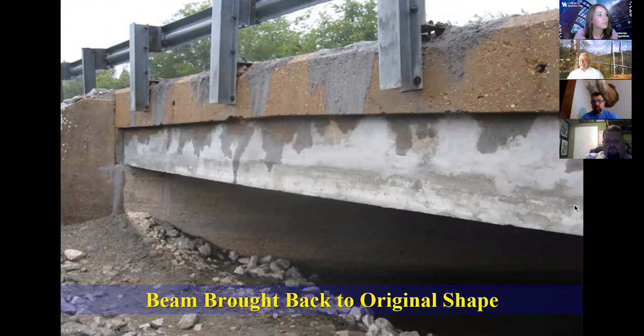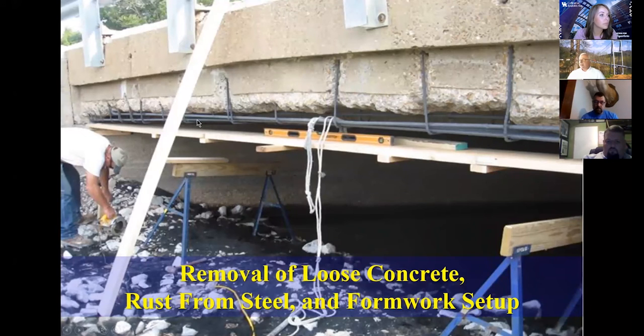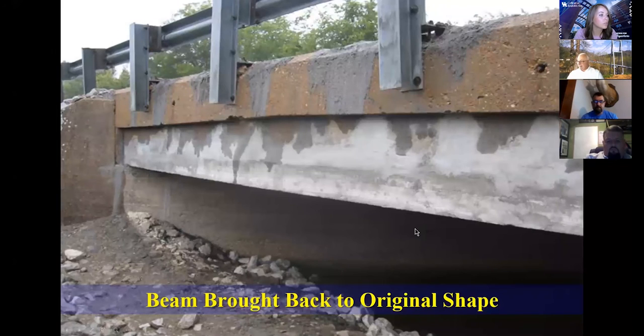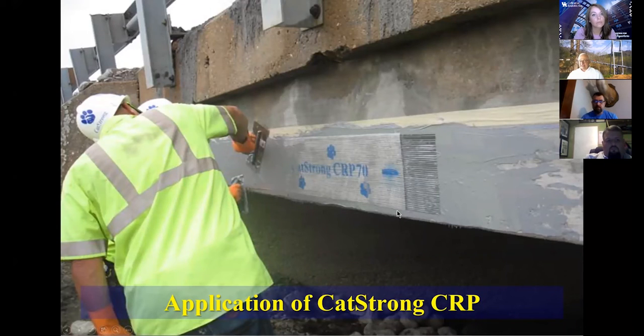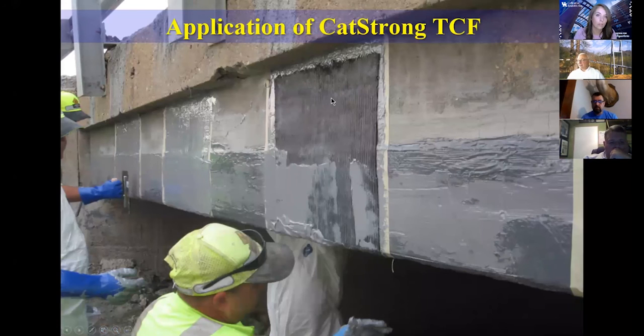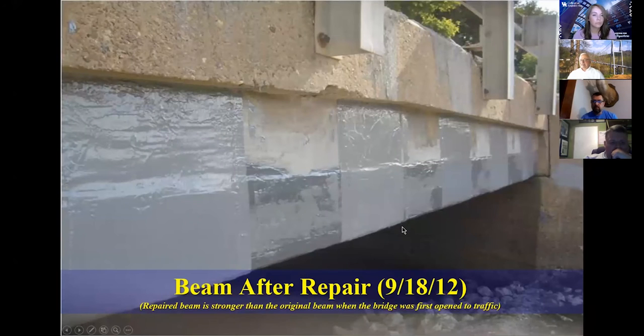So after we bring the beam back to its original shape, what happened in here is that some of the steel rebars lost about 70% of their areas. So, which meant that, of course, we have to replace that steel. So we could replace it internally or externally. So if we use the CRP panels, we can replace the steel that's lost externally. We put some on the soffit of the beam and some on the side of the beam. And it had lost also some shear capacity, and these fabrics in here are for additional shear capacity for the beam. So again, all the reinforcement now, instead of being inside, is on the outside of the beam. And this is the finished product.